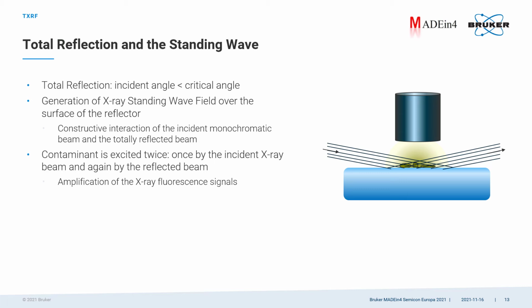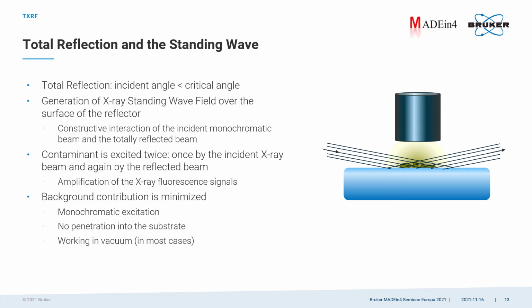So you can say that by the standing wave, the contaminant is excited twice, once by the incident and once by the reflected beam, and therefore amplifying the fluorescent signal. To be able to detect the smallest traces, it is important that the background in the measurements is as low as possible. So this is firstly achieved by the monochromatic excitation, and by the fact that the X-rays do not penetrate into the substrate. And also typically we work in a vacuum. And altogether this leads to excellent detection limits down to E9 atoms per square centimeter. And also for TXRF it is a non-destructive technique and it does not require any sample preparation with chemicals.